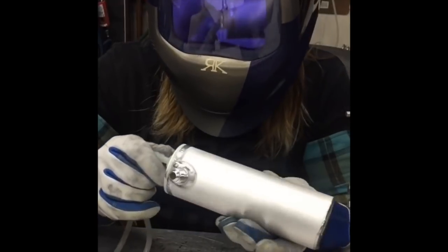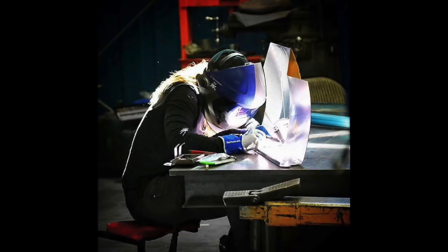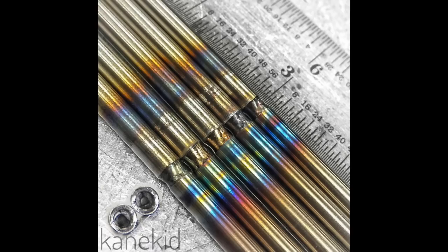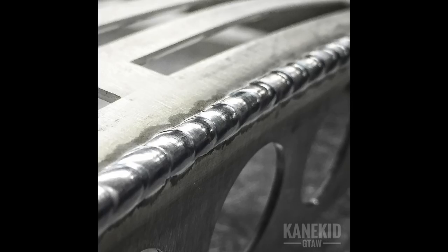A lot of that stuff is a little bit smoke and mirrors because it's not only the amperage but the time of the amperage, and they're able to advertise a 1 amp start. Whereas a transformer machine like that, it's a little different. But anyway, it's impressive that you're able to do those tiny little thin wall parts with that machine. It's a really good machine, particularly the one machine that I run, and I spent a lot of time with it and learned a lot of how to work the machine too, and how to work my foot pedals. When I weld those little parts, I rarely turn my peak amperage on my machine to less than 100. It's usually set between 100 and 130 amps. So you have it at 130 amps for thin wall tubing? I'll usually back it down to 100. Still.